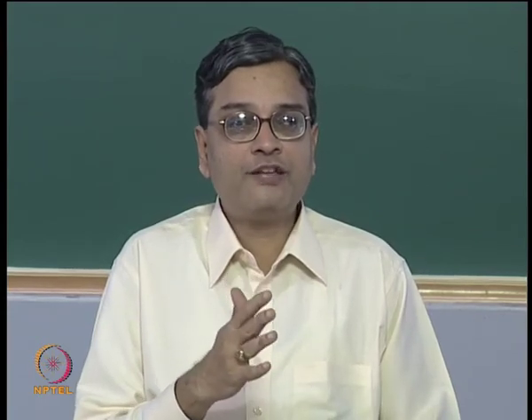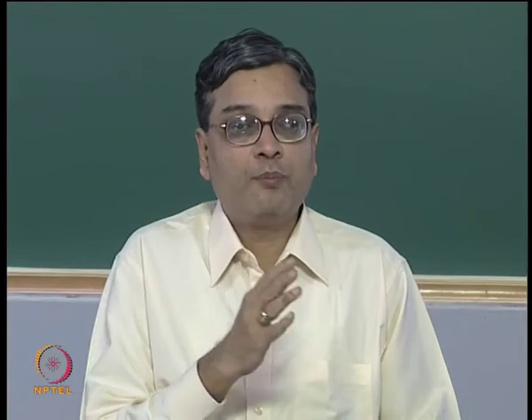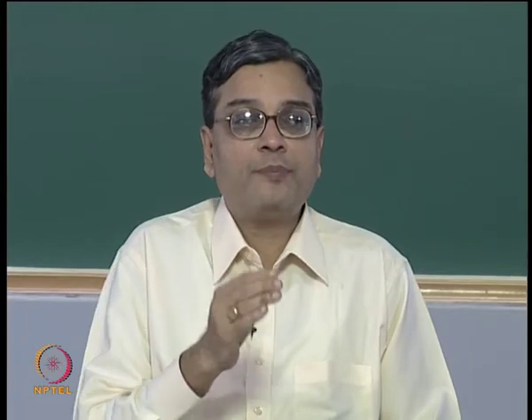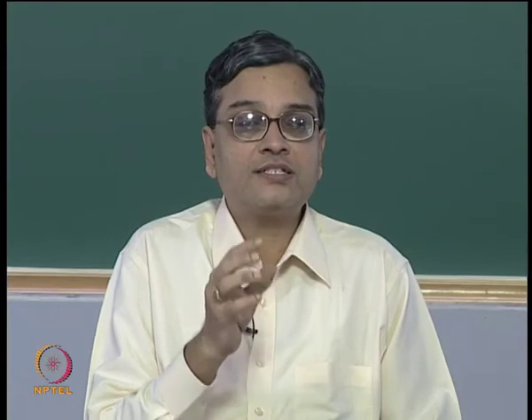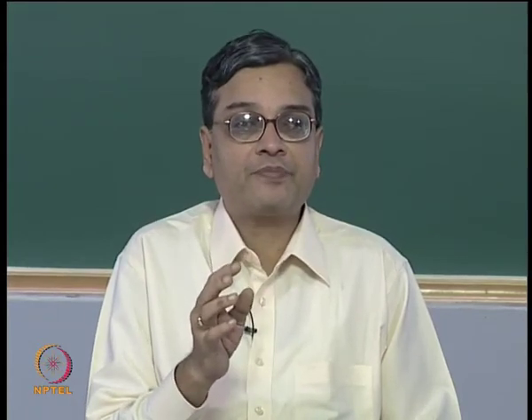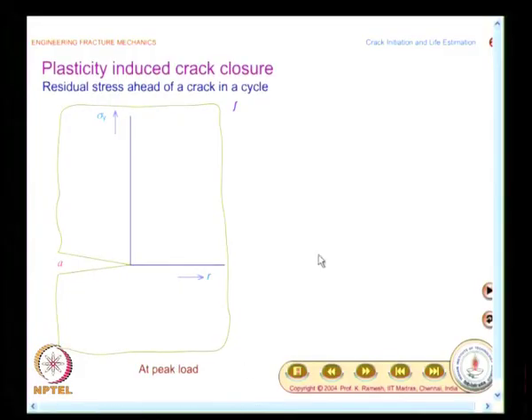Then we also had a brief look at the effect of overload. In both the cases, what you will have to understand primarily is, because of repeated loading, there is a residual stress created ahead of the crack tip that forms a basis, and we will again have a look at it to understand it better. And that is what is mentioned here. What is the residual stress ahead of a crack in a cycle? We first look at what happens when the load is increased from 0 to the peak load. This is the first part of the cycle, and you have the crack and the crack axis here,